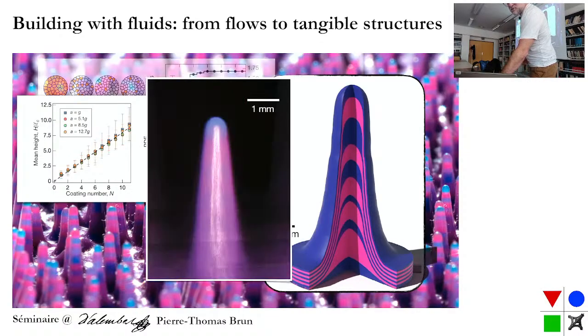What you can do is take an average of all these shapes. And if you take an average of all these shapes, you grow to something that looks a bit like a cone. And essentially, this is not a big surprise because you're stacking things that grow linearly with the number of coatings. And then you're adding a little bit of a thin film, which is also proportional to the capillary length. And if you combine these two things, and I go a little bit fast and I'm a little bit casual, you can prove that essentially you have a cone with a specific angle, and you can integrate this sort of stereotypical shape, and you find something that looks like that.